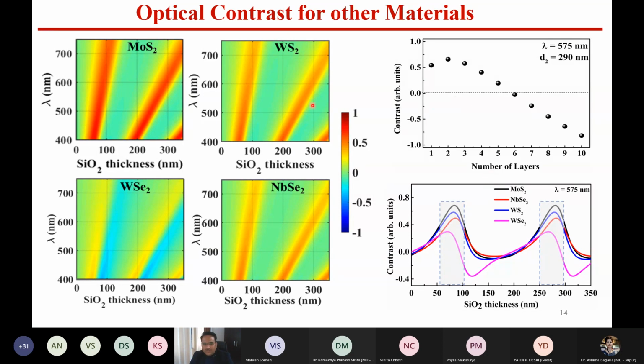So using this particular method, we have identified that a thickness close to 60 nanometer to 100 nanometer, and another one of 250 nanometer to 300 nanometer, are the thicknesses of the silicon oxide which are more appropriate for these kinds of materials, especially for the visibility of the monolayers, especially in the yellow light here.